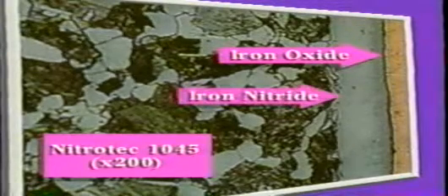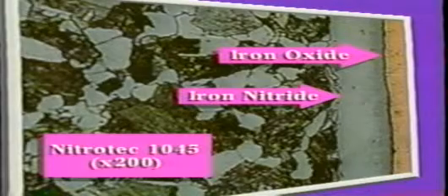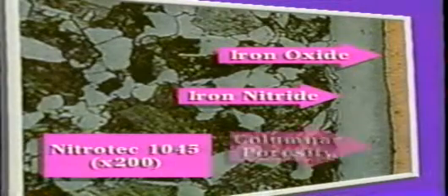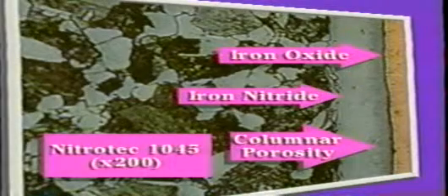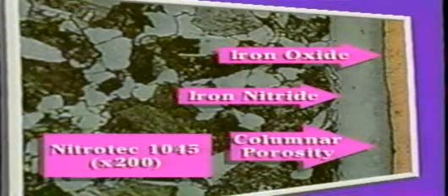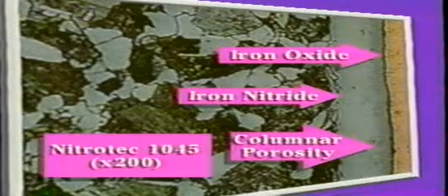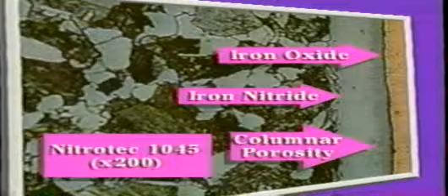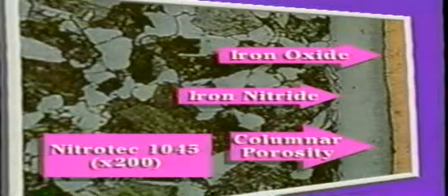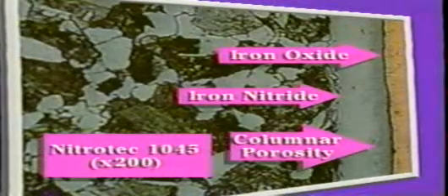layer of iron nitride. If you look closely, you'll see that the iron nitride layer has what is called columnar porosity to about half its depth. This controlled porosity allows the iron oxide to fill the pores, which dramatically increases corrosion resistance. In addition, the oil-carrying capability of the pores significantly improves surface lubricity and further contributes to corrosion resistance.